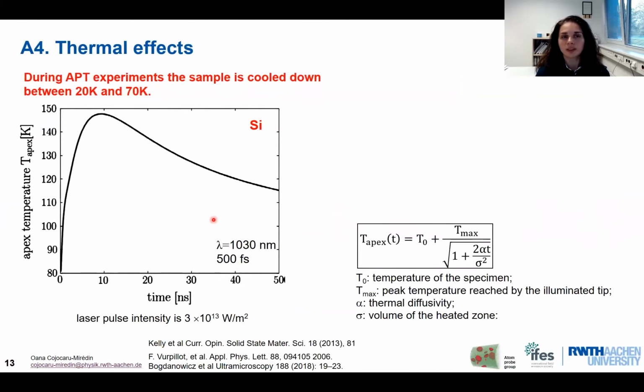But now there are some very nice experiments which have been performed by Kelly and co-workers, and they have measured the temperature at the apex of the tip. It is important to mention here that, compared to the work of Sundaram, they have measured the temperature increase on the sample when the sample was kept at room temperature. Our atom probe experiments are actually cooled down at cryogenic temperatures between 20 and 70 Kelvin. This is a very important condition.